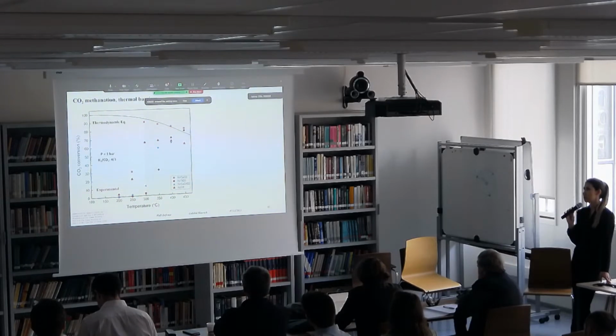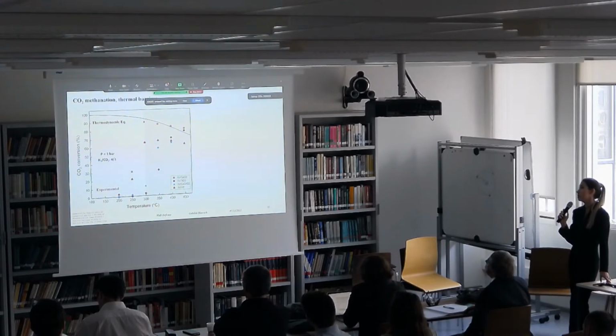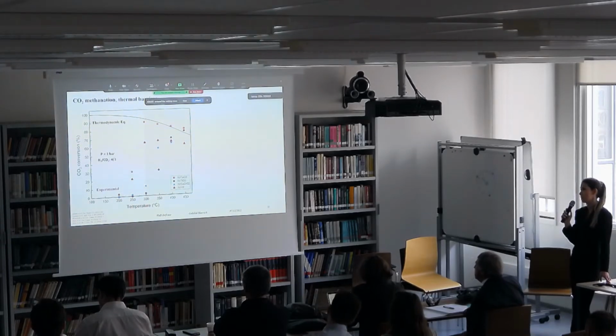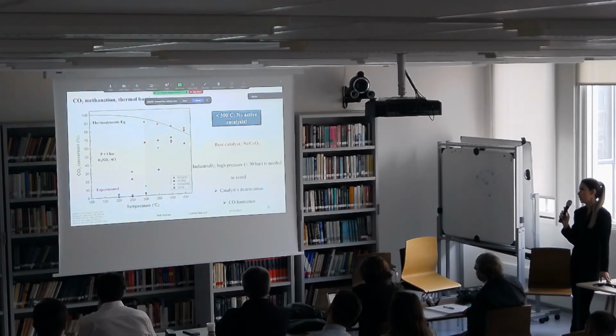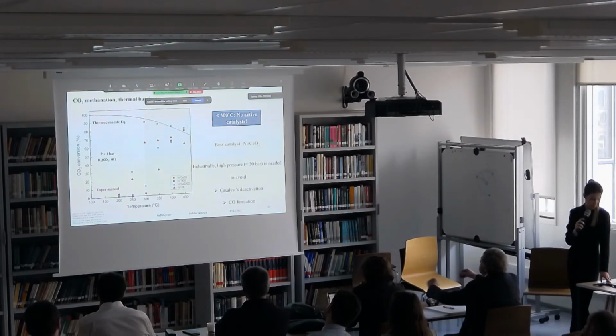So as we already discussed, CO2 methanation is thermodynamically favorable, but there are some barriers. In order to show you these barriers, I gathered some data from some nickel-based catalysts in CO2 methanation. All the reactions were done at atmospheric pressure and between 200 to 450 degrees. As it can be seen, the best catalytic performance was for nickel ceria. However, for all the catalysts below 300 degrees, there was no activation. Also, the fact that in industry it should be done at high pressure in order to avoid catalyst deactivation and CO formation brings some obstacles which need to be overcome by some methods.